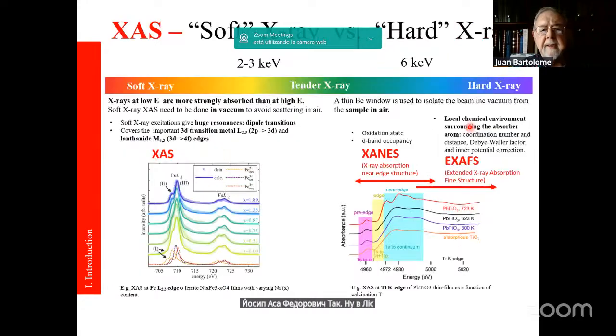Now, this XAS technique can be performed in what we call the soft X-ray range, so at lower photon energy. These photons are absorbed by air, so the experiment has to be done at high vacuum because of scattering. And usually we get very strong absorptions due to the dipolar transition probability. It covers the 3d metal L2,3 edges, which is very important in magnetism since we are then populating the 3d states or bands from where the transition metal magnetism stems, or also lanthanides at the M4,5 edge, because we are populating the 4f states of these elements.